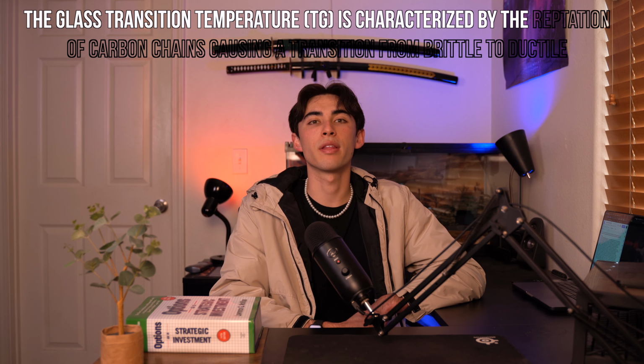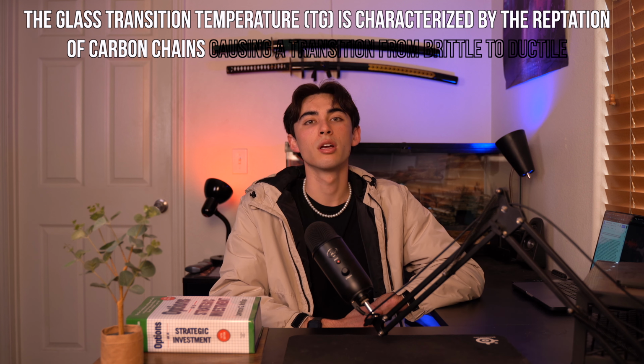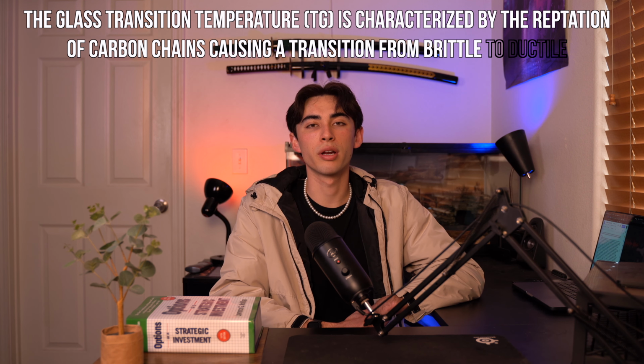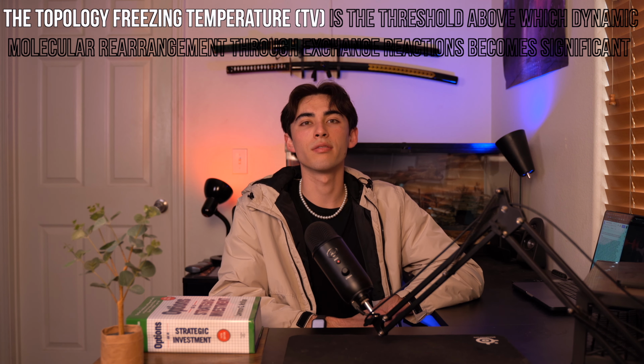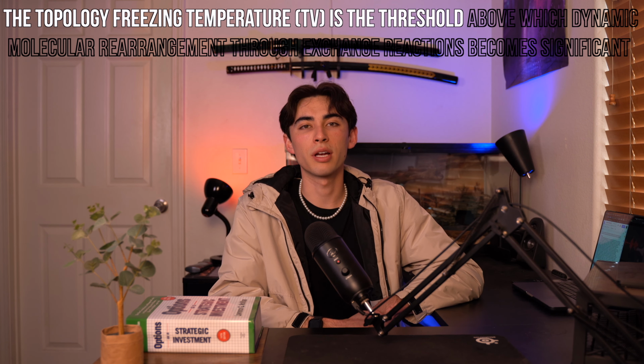Below the topology freezing temperature, TV, Vitrimers act as thermosets, whereas above the TV, Vitrimers flow with an Arrhenius trend, being viscoelastic, reprocessable, and reshapeable. Though the glass transition temperature and topology freezing temperature seem similar, TG is characterized by the reptation of carbon chains causing a transition from brittle to ductile. TV, however, is the threshold above which dynamic molecular rearrangement through exchange reaction becomes significant.